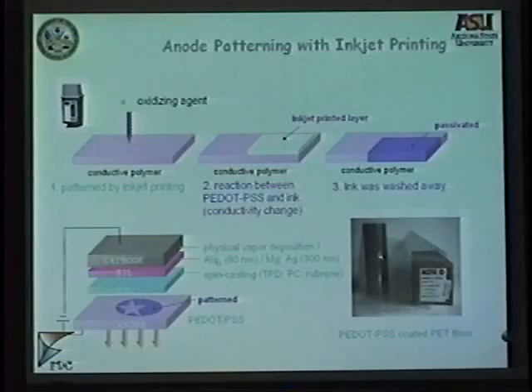Okay, and this is perhaps the most economical way to make patterns without any mask, and it's not a contact method, it's all non-contact lithography, because the inkjet doesn't even touch your substrate, it just gives you the drops. Now in this method here, we are doing something unique. We take roll-to-roll plastic substrates that are already coated with PEDOT:PSS. Before we were printing PEDOT:PSS; in this application, we bring in the substrates, which are donated to us by AGFA.